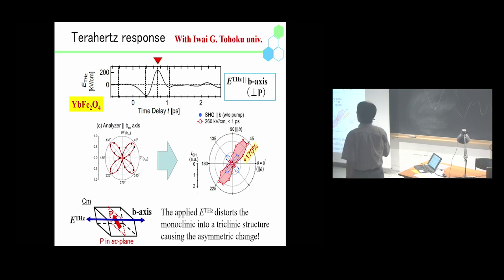This is the angle dependence of the SHG before the photoexcitation, as I told you. You can see a four-leaf type azimuth angle dependence. However, if we apply this terahertz field along the b-axis, then we observe a huge change of the angle dependence of the SHG. Along this direction, the SHG magnitude increased by more than 170%. This is the largest value as far as I know in the case of ferroelectric materials.